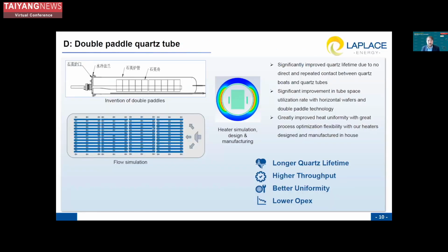The other one that I was mentioning was double paddle quartz. Here we work again on the lifetime of our quartz material. We invented double paddles so that we don't have any direct contact between the tubes and the boats. This increased the lifetime of the quartz parts significantly. We also could improve the space utilization again and the uniformity, as we get a better control of the gas flow within our systems and therefore also of the homogeneity of our depositions or diffusions. And all of this then brings down the OPEX.